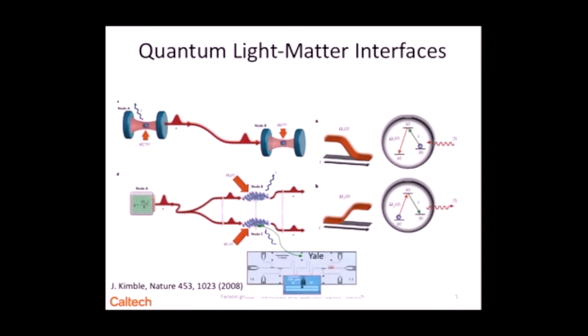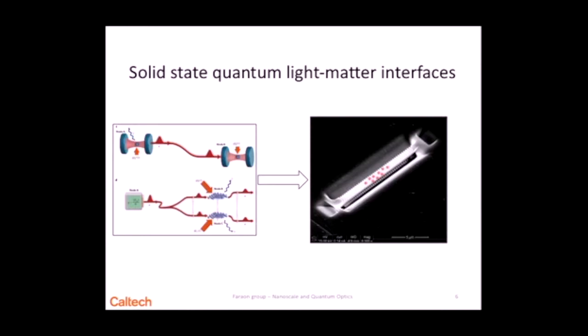This type of device was proposed initially in the context of atomic physics. However, we are interested in developing them in solid state, so instead of having single atoms or single trapped ions coupled to microscopic optical resonators, we would like to make devices where the optical resonator is made out of a solid-state material. In this case it's a photonic crystal resonator, fabricated in one of these complex oxides — in this case yttrium orthosilicate — and the atoms are actually sitting embedded inside this optical resonator, as shown schematically.